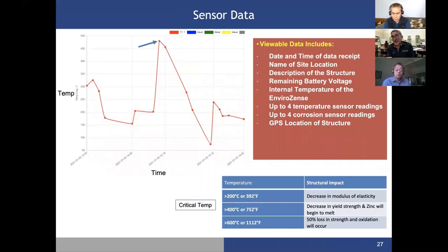So let's see what type of data we get. The left-hand side shows the graph of temperature versus time. And you all saw in the video that Clinton showed this process takes place very rapidly. So you are monitoring the temperature versus time, and we already defined 3 ranges of critical temperatures, 200, 400, and 600. So by knowing this graph, immediately during and after wildfire exposure, you will know what structures should be paid attention to and condition assessment should be taken immediately afterwards. Those that go above 600 degrees C lose 50% of their strength and extreme oxidation may take place if the time of exposure is long.